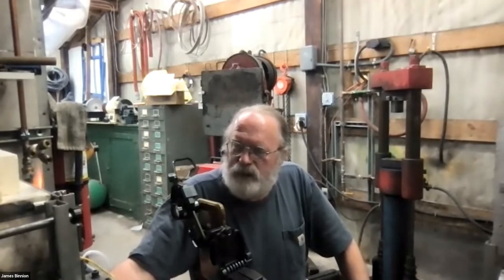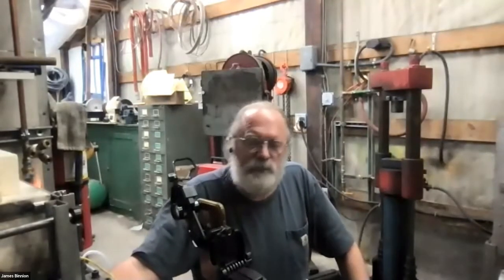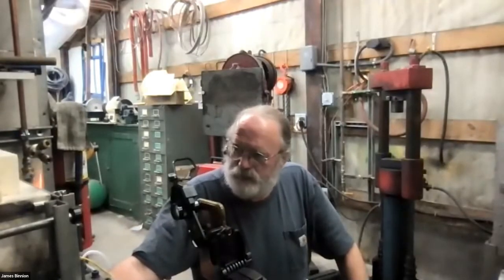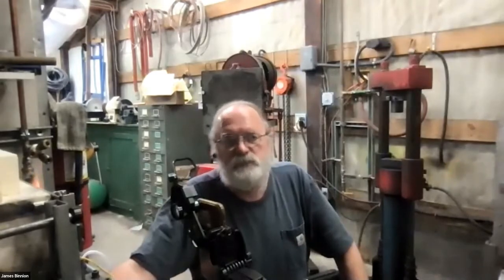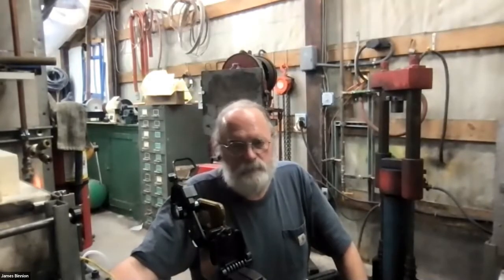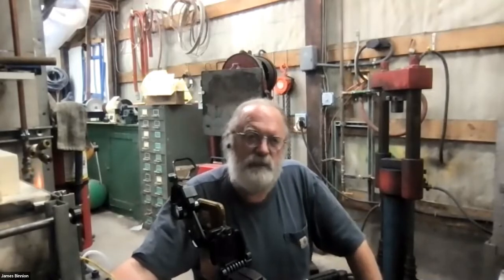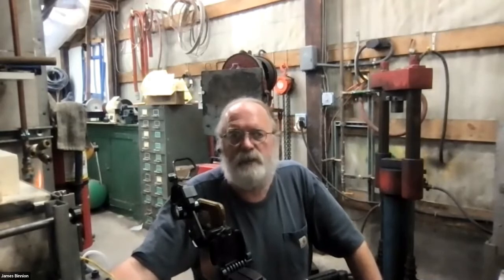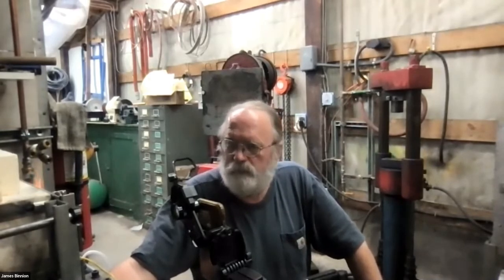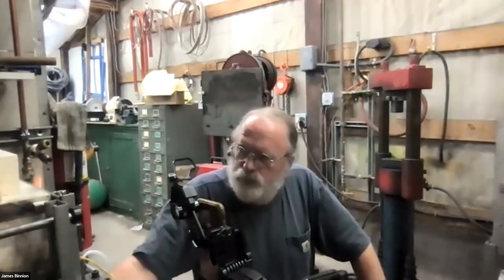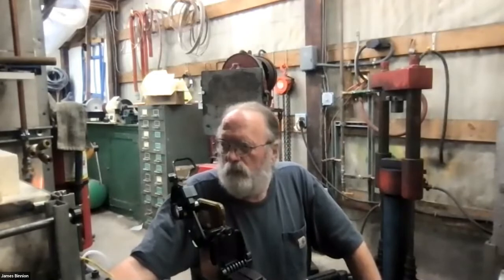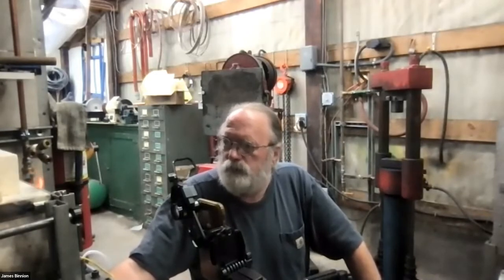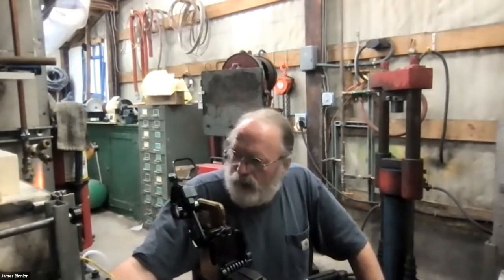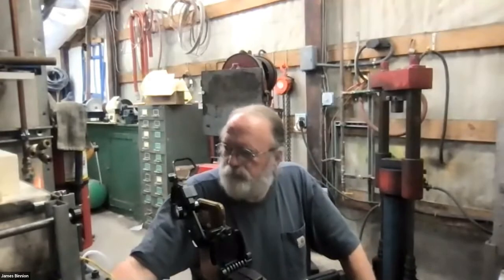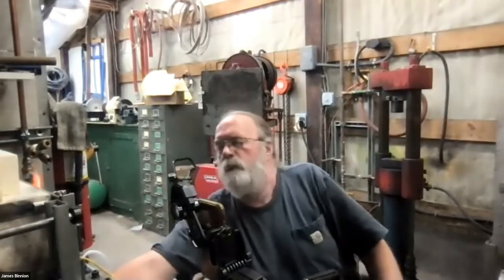I find that I want to cut through at least 3 or 4 layers during the patterning process so that I can get a couple of different layers of the material exposed. If you start cutting through too many, again, you start losing the impact of the pattern because you've got too much going on in there. I like to use a rotary carbide burr to do the carving, and I like to use a very high-speed pneumatic tool to do that.